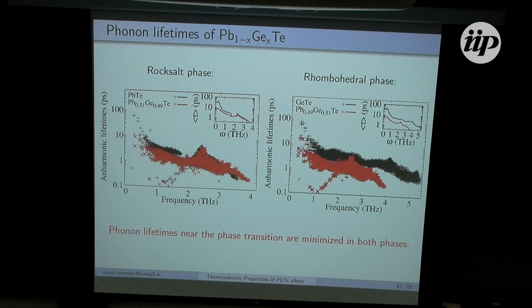Now it might be a bit difficult to see there. So again, if you look at this inset in the top right, which shows the averaged phonon lifetimes as a function of frequency, you can see there's quite a nice reduction there at lower frequencies, where at higher frequencies, not so much is happening. Now if I take a look at the rhombohedral phase here, again the anharmonic phonon lifetimes, germanium telluride in black, and this alloy composition on the verge of the phase transition in the rhombohedral phase. And we see, in this case, we have quite a nice reduction in the phonon lifetimes. And again, to stress in this case, we see that the lifetimes are reduced across the frequency spectrum by quite a large amount. But what is most important in this slide is the fact that these anharmonic phonon lifetimes are minimized at the phase transition.